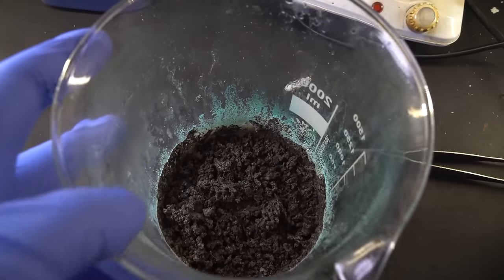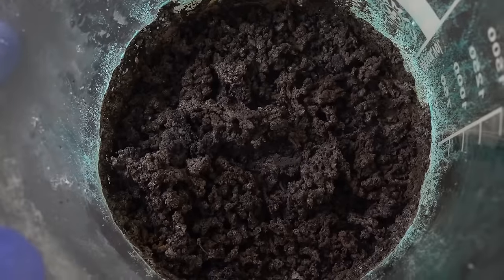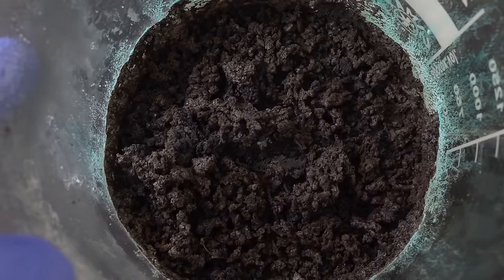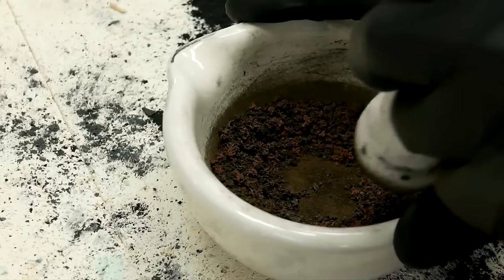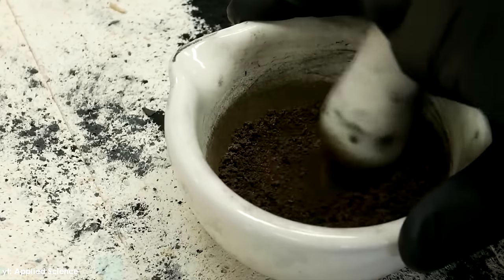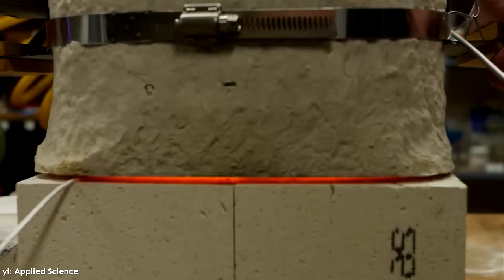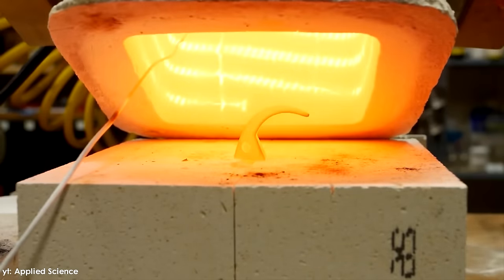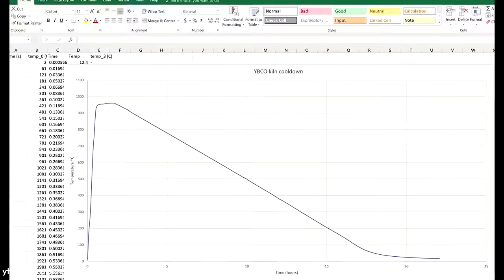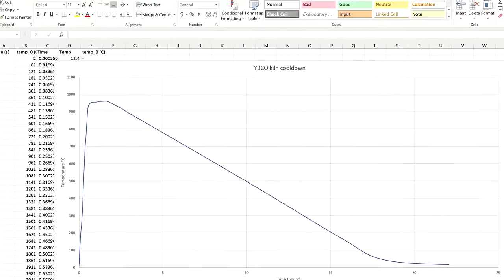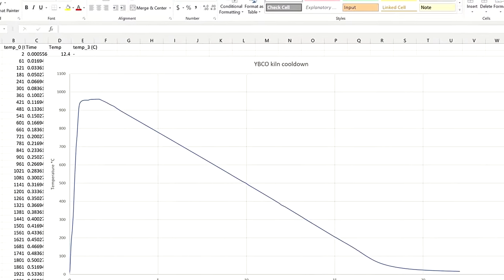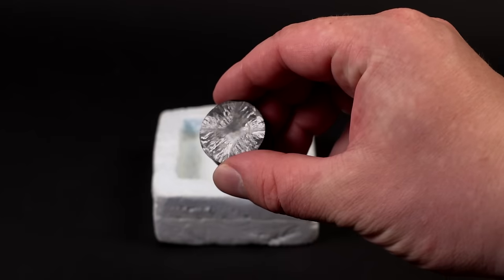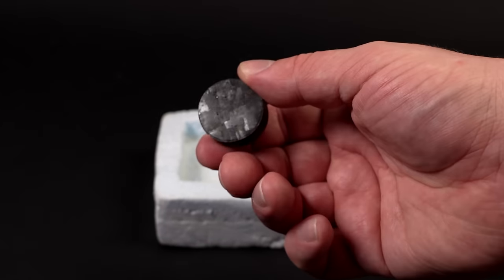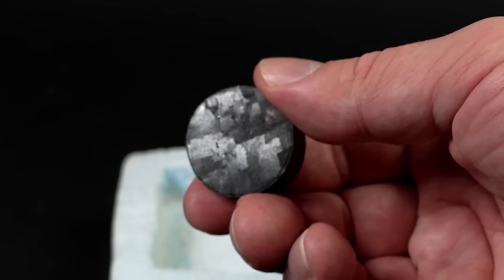After all this, the resulting mixture hardly resembles ceramics. In order to produce a superconductor, the resulting oxide mixture has to be crushed, compressed, and baked in a muffle furnace with the addition of pure oxygen. Moreover, the baking has to be conducted at a decreasing temperature, so the required crystals of a certain size and chemical composition could form in the ceramics, thus providing it with the above-mentioned unusual superconducting properties.